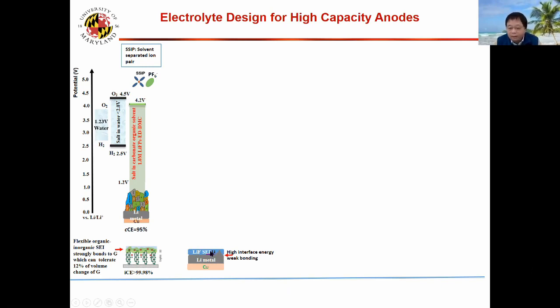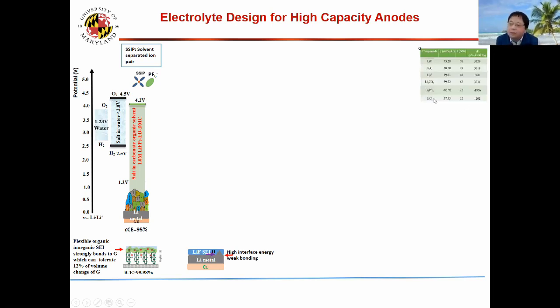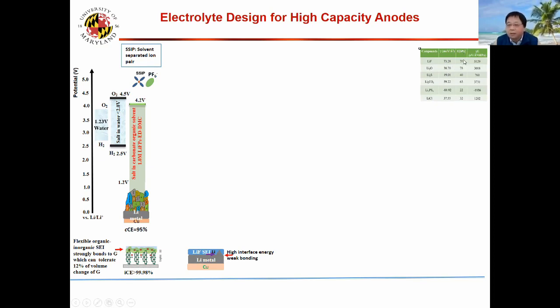There are so many ceramics or polymers — which one has the highest interface energy? Generally, polymer has lower interface energy; ceramic has high. Among ceramic SEI components, lithium fluoride has the highest interface energy. And if we also want good mechanical properties and multiply these two values together, lithium fluoride is the best. Lithium carbonate is fine, but lithium sulfide is not good. That's a real challenge for solid-state right now.